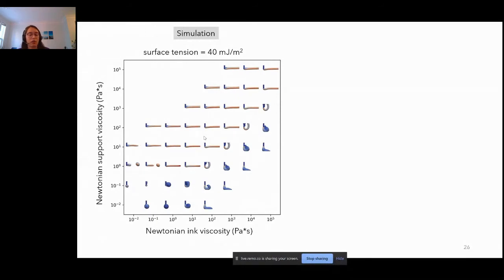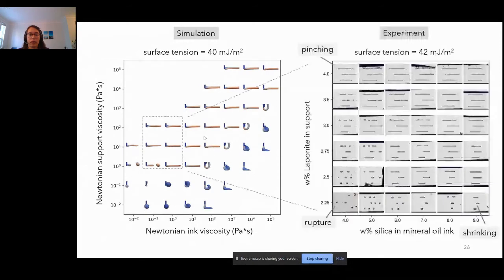a singular droplet. If we compare that to our experiments, these experiments are covering a smaller region of this viscosity map in terms of the local viscosities, but you can see we get the same pattern, where at low support viscosities, we get filaments that break up into droplets or start to go towards a spherical shape. And if the ink viscosity is low, you get filaments that break up into droplets. If the ink viscosity is high, you get a full filament that then shrinks back towards a spherical shape.